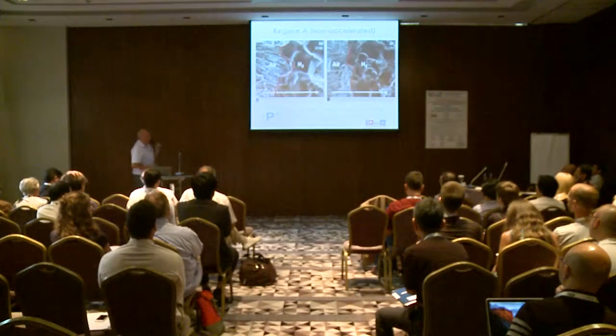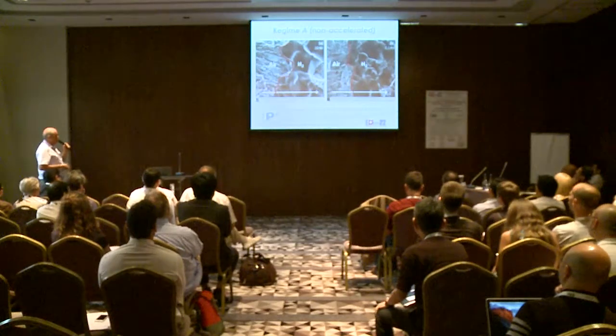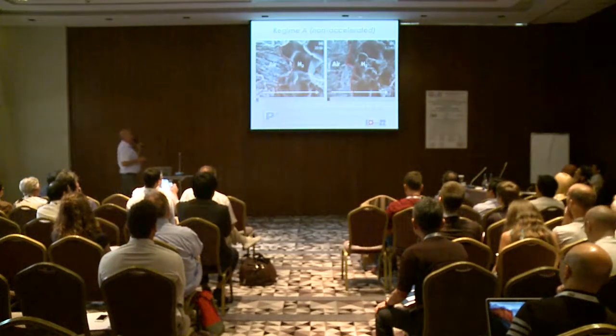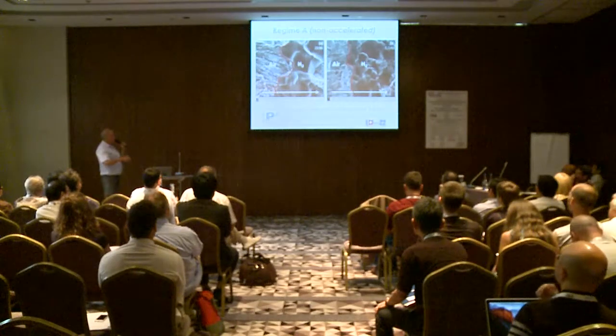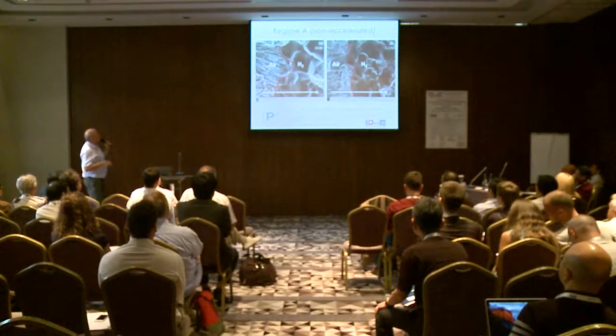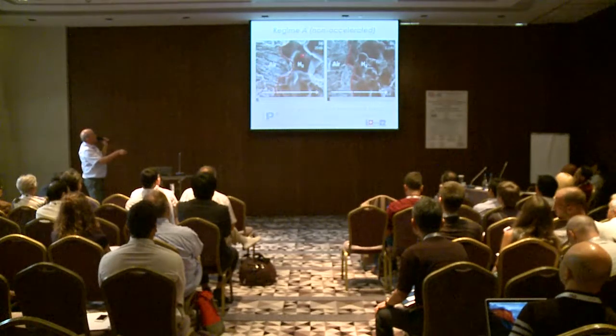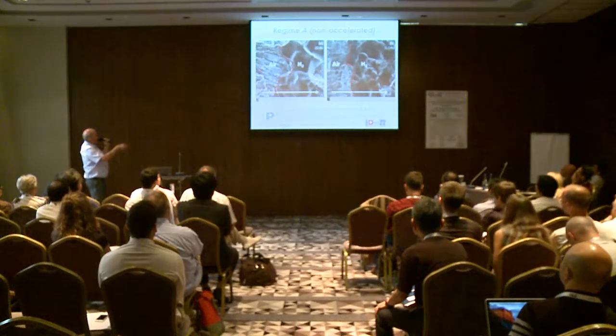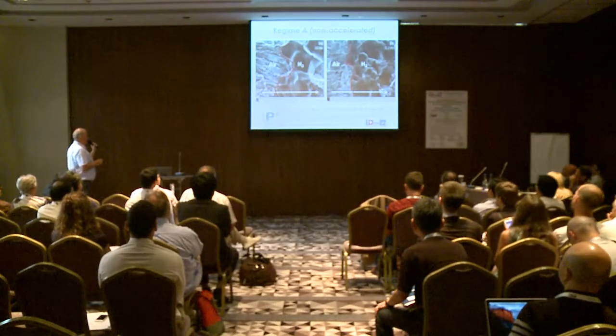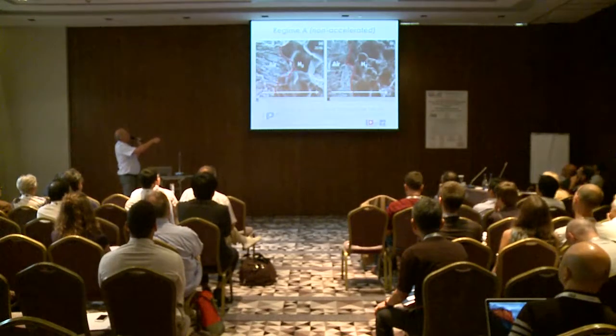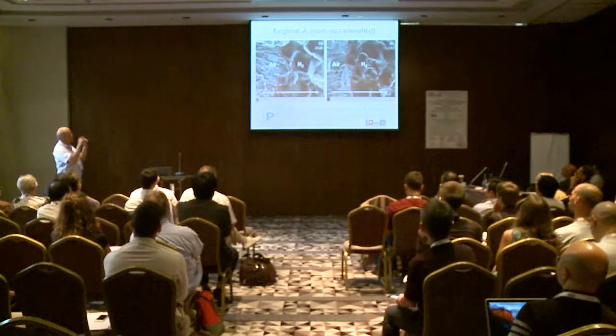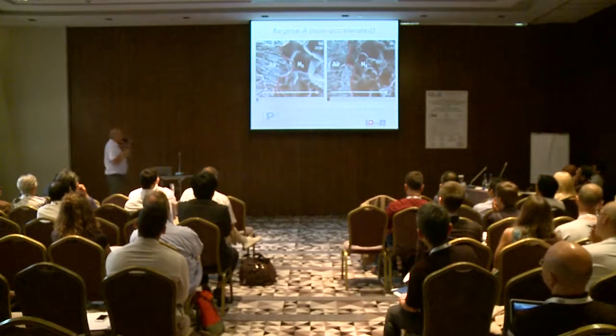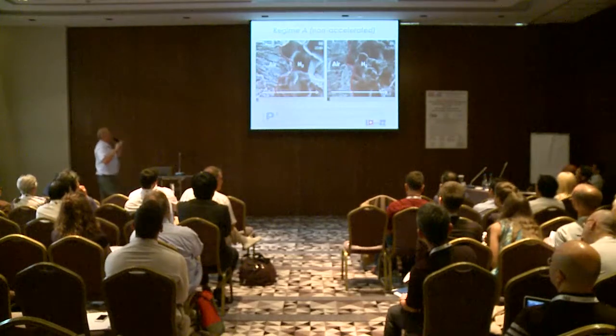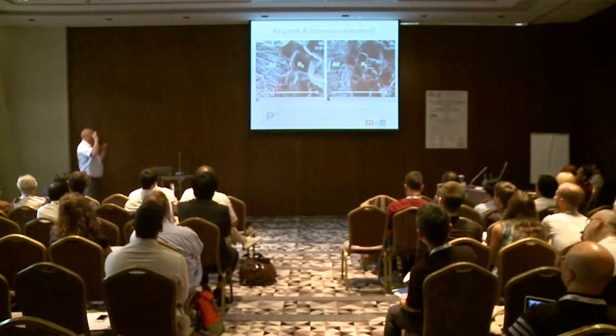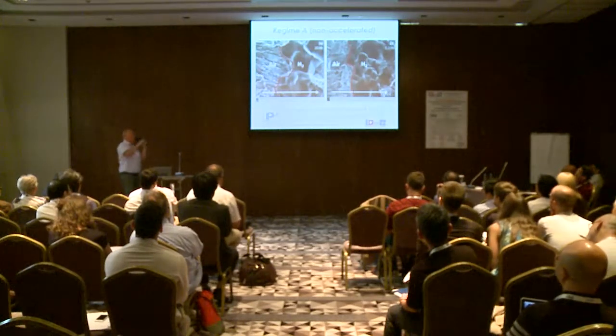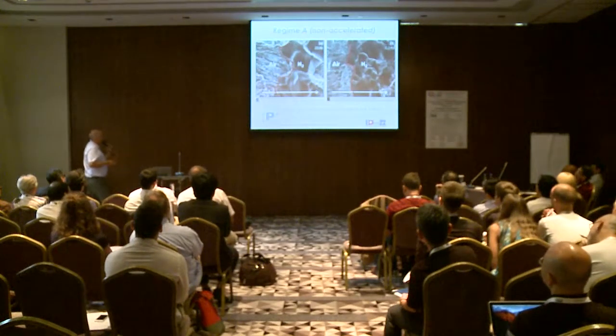Now, if we look at the cracking mode, what is really surprising in this material is... Here you have two observations at different frequencies. This is the fracture surface produced by the pre-cracking in air. And you can see that as soon as we introduce the hydrogen gas within the pressure vessel, we have a drastic change in the fracture mode, from a fully transgranular towards a fully intergranular cracking mode.